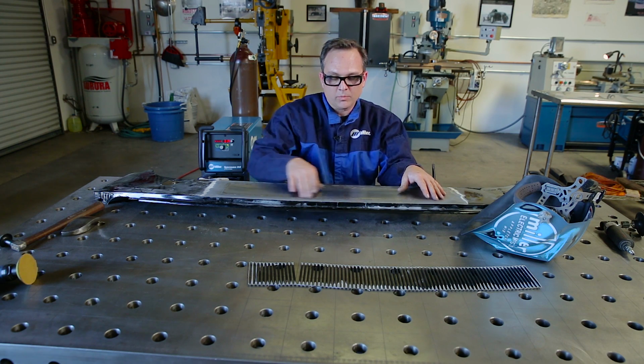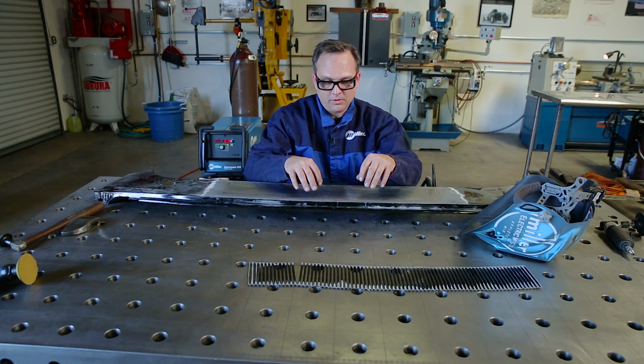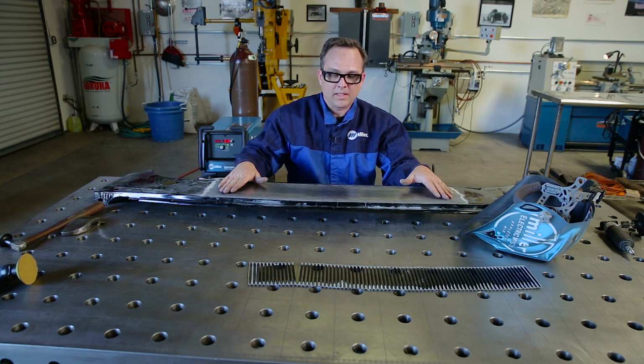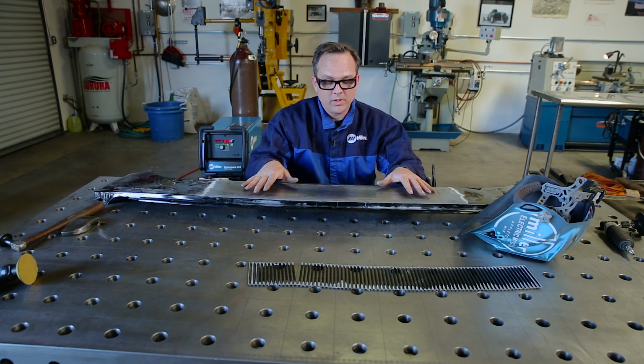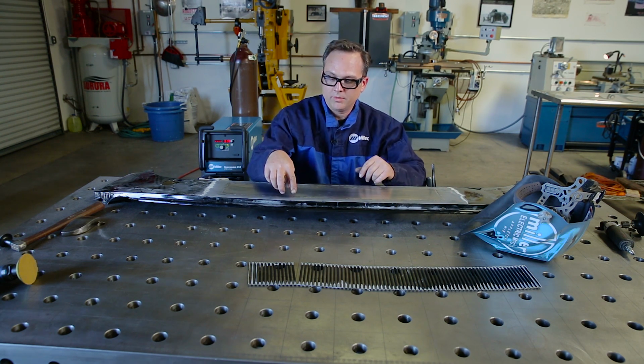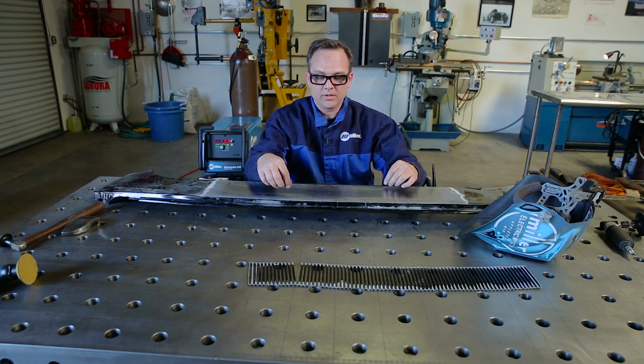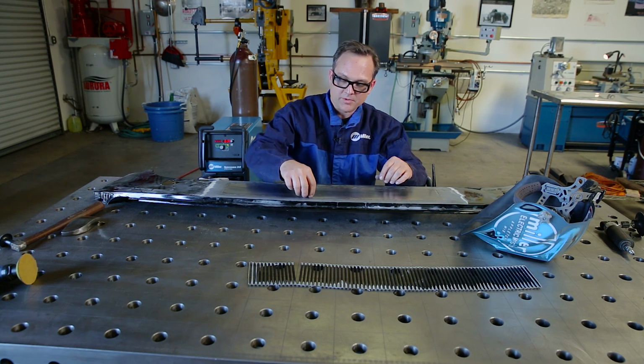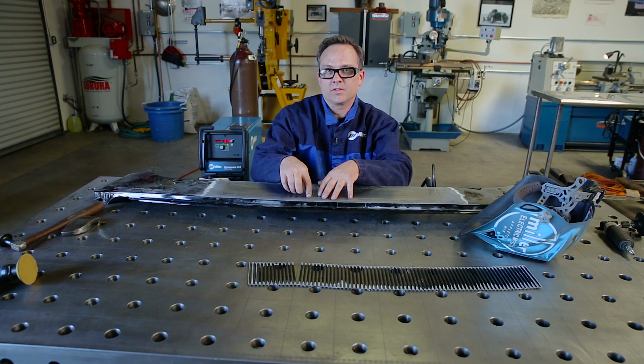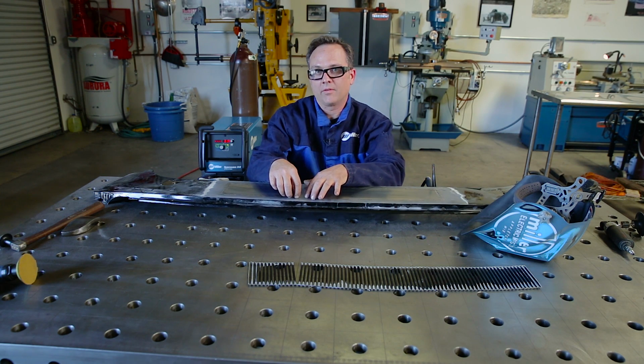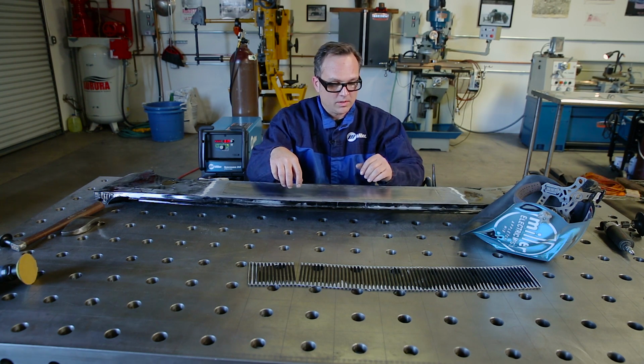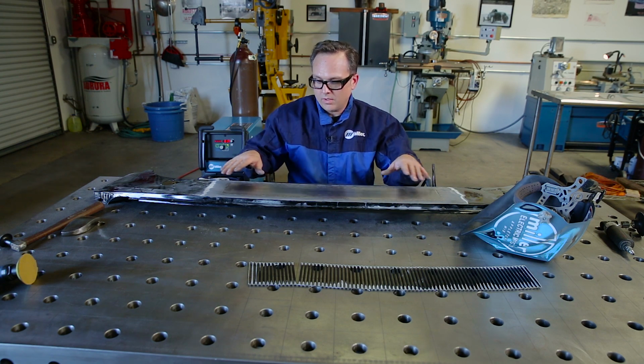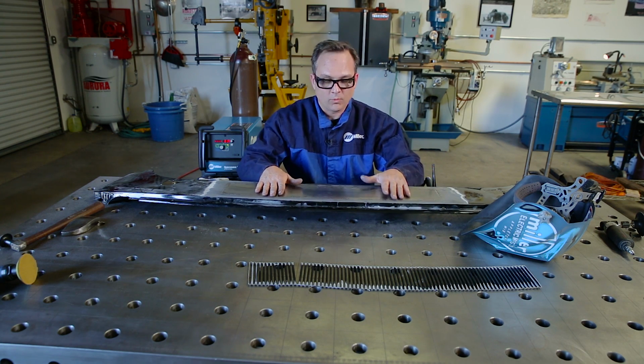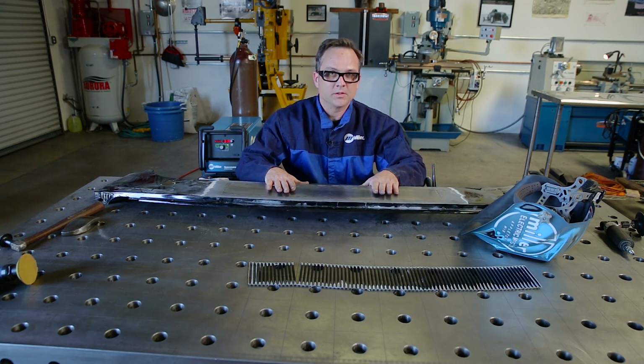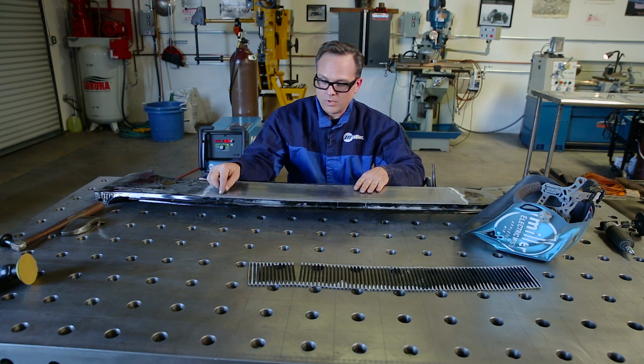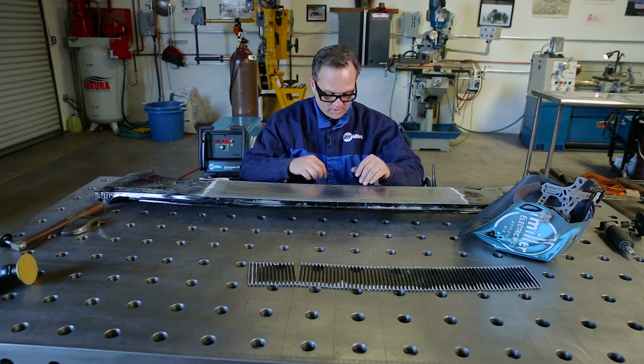Then when you go back and planish your weld, you're planishing it even. So basically that keeps everything even all the time. If you skip around, you shrink this area, and then you shrink this area, and you come back beside this one and shrink it, but it doesn't shrink the same because this one's holding it back from shrinking the same. So then you wind up with a wavy warpage throughout the whole thing, and you have to work that out later, which, to me, is a little bit harder. So I like to start at one end and just go to the other.